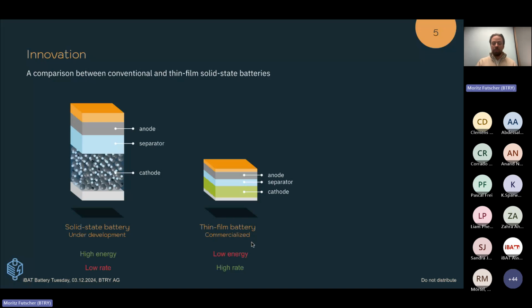However, we typically have them on a substrate. In research, this is even sometimes silicon wafers. They're very bulky. In industry, this is more thin metal foils. But still, these metal foils are typically in the order of 10 micrometers thick. And now if you assume you have a 10 micrometer thick foil, and a very thin cathode on top of just a tenth of the thickness, this is a poor energy density.